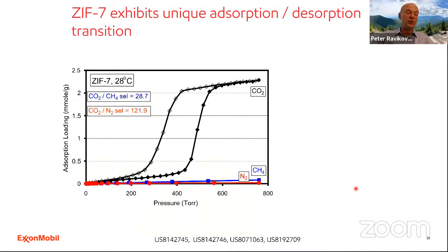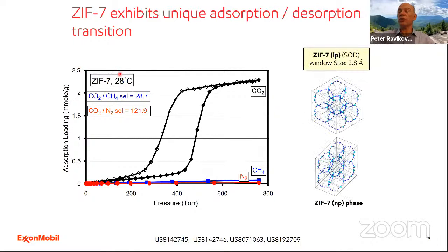The typical example is ZIF-7. ZIF-7 has a structure somewhat similar to ZIF-8, except it has a bulkier benzimidazole linker, but it shows very different adsorption behavior from the typical Langmuir isotherm. It shows a so-called type 5 isotherm with a prominent step: no adsorption until a certain pressure, and then a sudden transition. Usually on desorption, this transition is associated with hysteresis. What is interesting is that some molecules can open the structure, like CO2, and some molecules cannot open the structure, at least in this range of pressures. So what happens here is actually a transition between the so-called narrow pore phase and the large pore phase of the material.